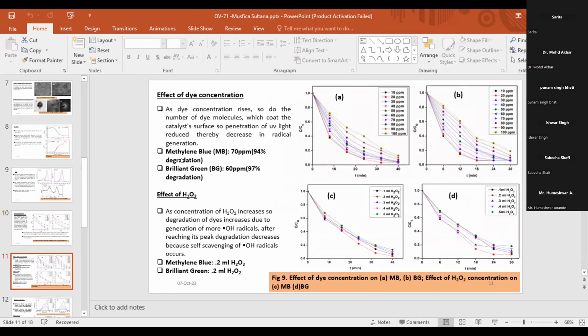When dye concentration is changed, it is seen that methylene blue gives 94% degradation at 70 ppm. And for brilliant green, at 60 ppm, 97% degradation has occurred. But after that, the degradation efficiency decreases, because as dye concentration rises, so does the number of dye molecules which coat the catalyst surface. So penetration of light is reduced, thereby decreasing radical generation.